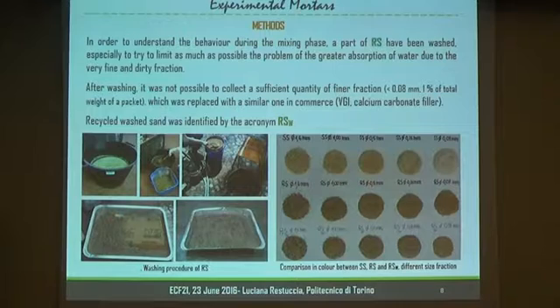After washing, it was not possible to collect a sufficient quantity of finer fraction, that is the 1% of total weight for the packet of standard sand. And for this reason, we replaced the finer fraction with a similar one in commerce. In this case, we used a calcium carbonate filler. The recycled washed sand was identified by the acronym RSW.